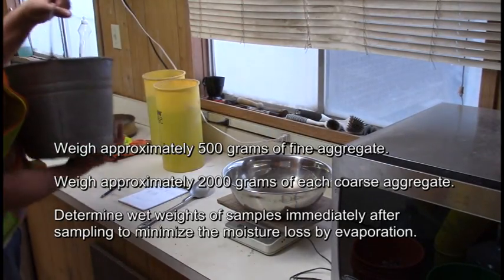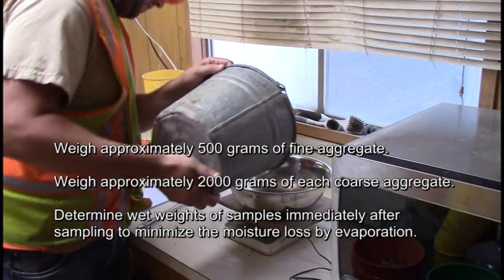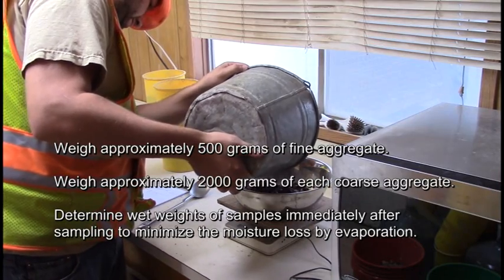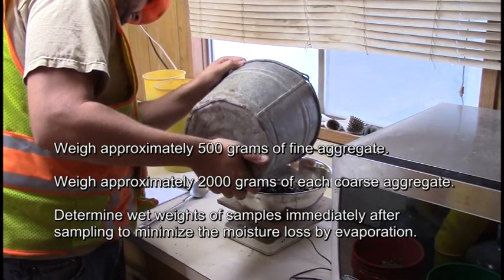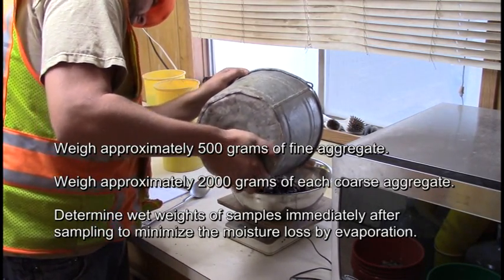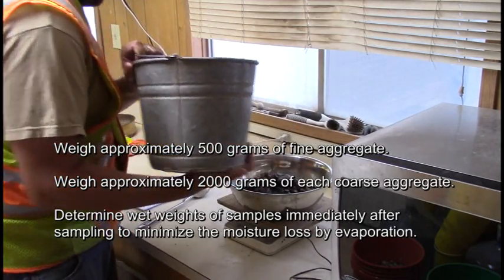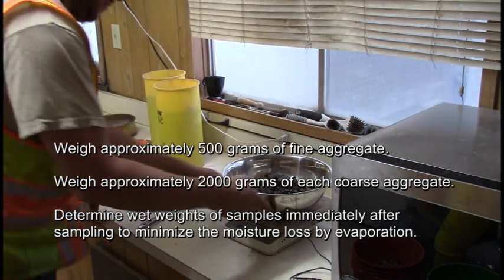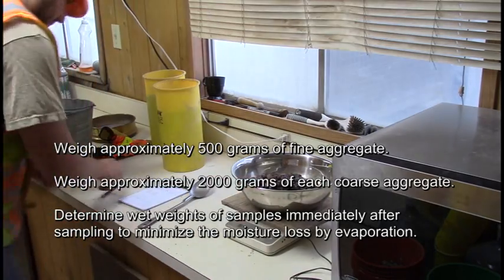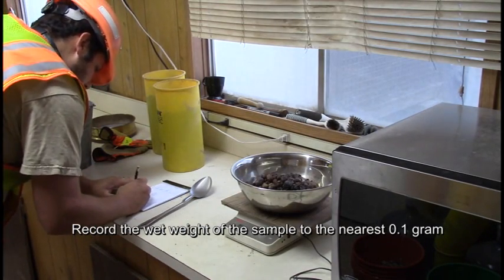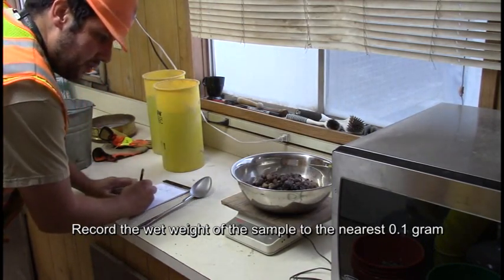Weigh approximately 500 grams of fine aggregate. Weigh approximately 2,000 grams of each coarse aggregate. Determine wet weights of samples immediately after sampling to minimize the moisture loss by evaporation. Record the wet weight of the sample to the nearest 0.1 gram.